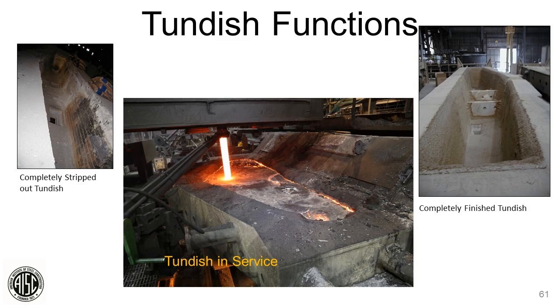The steel running on this is corrosive. We'll actually lose some of that, and it'll go away. So that's why we consume some of it, and then we come back and replace it after we tear it out. The middle picture is the Tundish. You can see there's a flux on top of that to prevent oxidation, and the liquid steel is going through the shroud and then being distributed by the Tundish to the caster molds. Next slide.